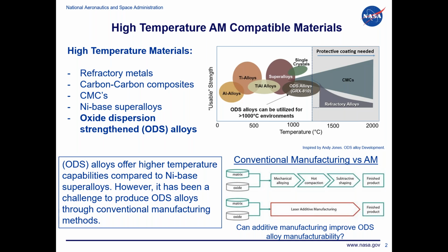And again, at those temperatures, the type of alloy systems that you can really tap into are pretty limited. A lot of them either have oxidation problems or printability issues for this application. What we want to do is try to explore this class of alloys called oxide dispersion strengthened alloys. In case you're not familiar, an oxide dispersion strengthened alloy is a metal that has nanoscale oxides incorporated into the metal part. And those nano oxides allow for large improvements in high temperature properties, stability of the microstructure, and a multitude of other properties like fatigue, creep, oxidation.